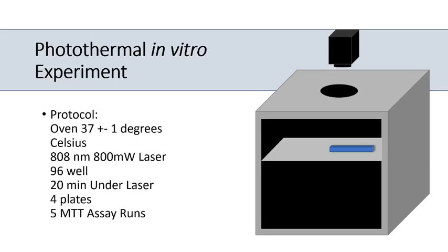When as many of the cells are dying as are in the really high toxic cells, there's not much absorption, it's very low. And so we need to make sure that the machine is actually reading it correctly. That's why we ran it 5 times, because it's hard when it's that low of a number for the machine.